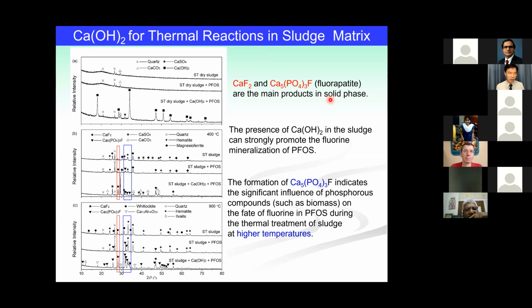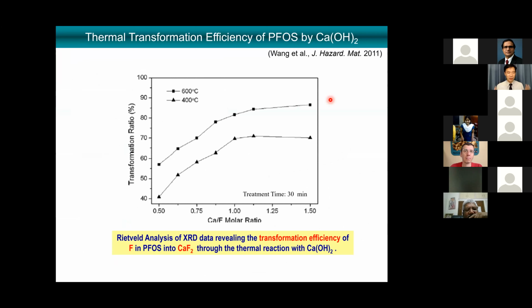Fluoroapatite, in fact, is a mineral that has the phosphate right there. And this is actually a very robust mineral, apatite. If you did a lot of soil remediation, you understand a lot of people use apatite, hydroxyapatite, put on the soil, and that will absorb the heavy metal, generate the apatite phase, and prevent the heavy metals from being leached from that phase. It's a very stabilized phase. And in fact, a lot of fluorinated toothpaste, or even the fluoridated water, tries to get the chance to react with our teeth to have a good fluoroapatite formed there. So it's actually a very interesting mineral phase that helps us in a lot of different directions. And we find this in a similar reaction process. So now we have two chances to help us stabilize the fluorine and prevent it from becoming perfluorocarbons.